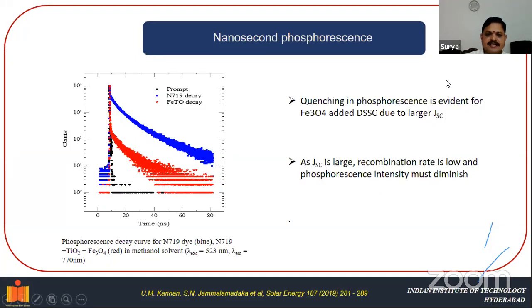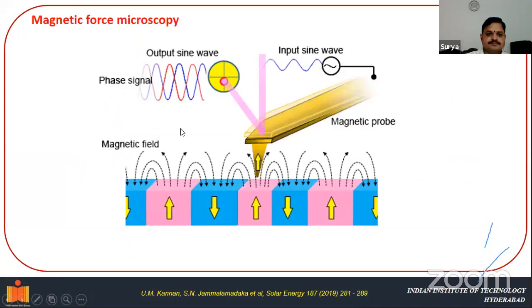A similar trend has been observed in the phosphorescence data. The quenching in the phosphorescence is evident for Fe3O4 added dye-sensitized solar cells due to larger short circuit current density. And as the short circuit current density is large, the recombination rate is low, and the phosphorescence intensity must diminish. Recombination rate is low, and as a result, the counts have decreased in the phosphorescence data.